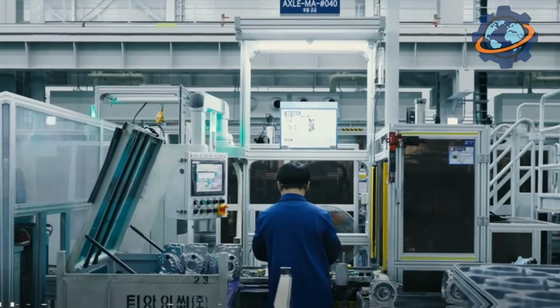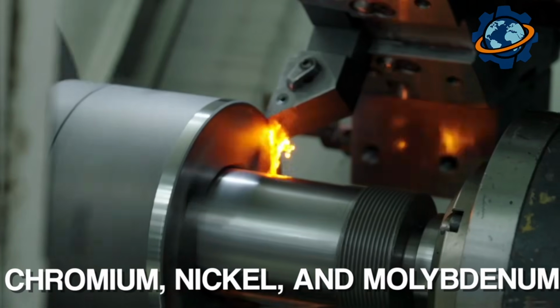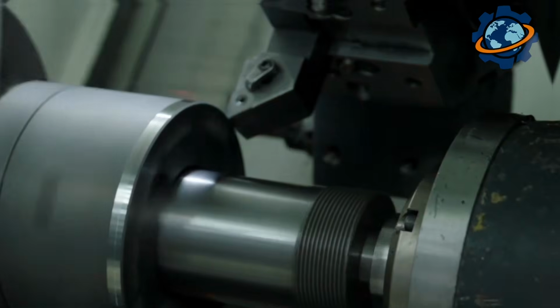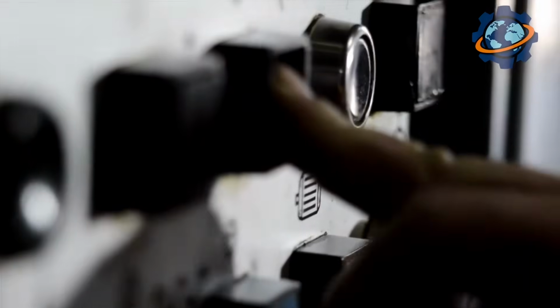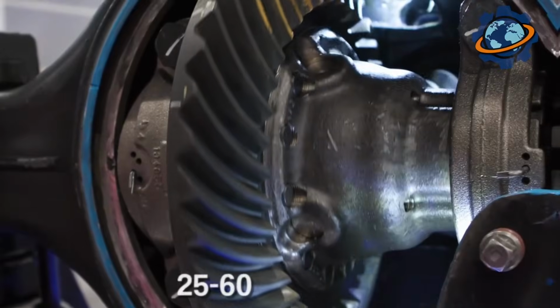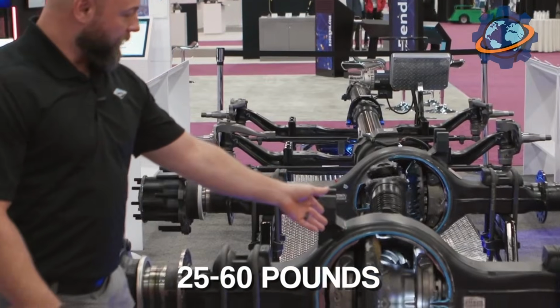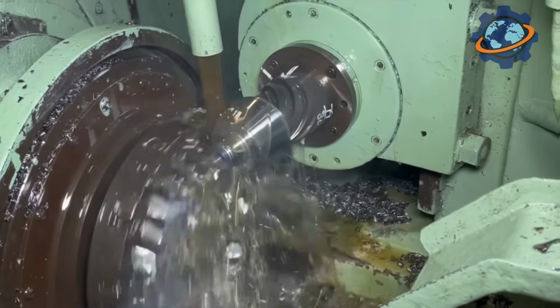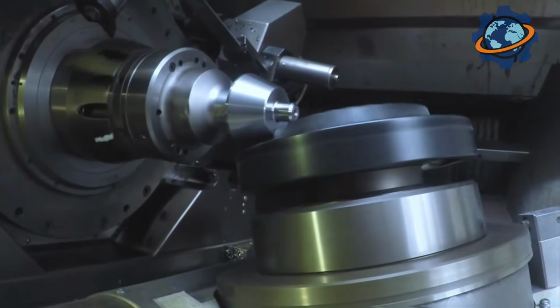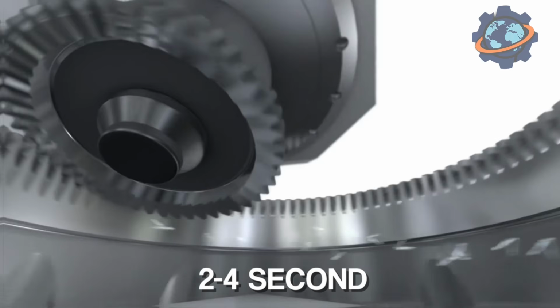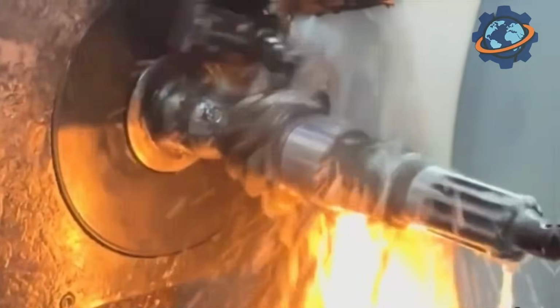Ring gear blanks are forged from alloy steel, the traditional chromium, nickel, and molybdenum formula. A ring for a heavy-duty axle has an outer diameter between 14 and 22 inches, and weighs anywhere from 25 to 60 pounds. The forging goes to a lathe where they remove the black scale allowance, then to a gear hobbing machine. The spiral bevel tooth is cut by a cutter head that simultaneously rotates and moves along a complex spatial path. A single pass on one tooth takes 2 to 4 seconds. A ring gear for a heavy-duty axle has 38 to 48 teeth, and the entire cutting cycle runs about 3 to 4 minutes per part.